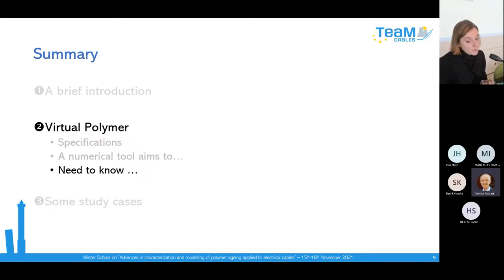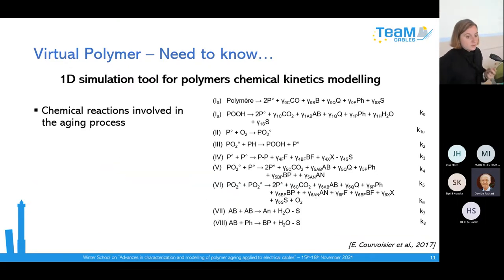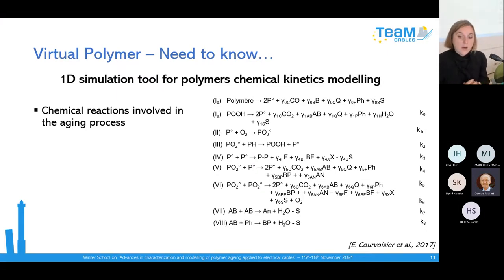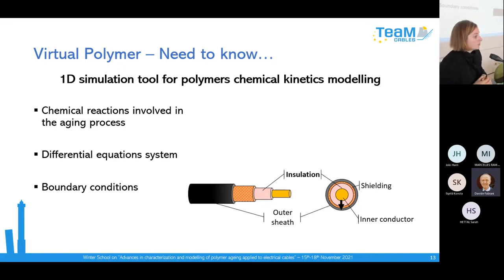For that, you need some input data. For virtual polymers, you need to know the chemistry of the polymer and the microstructure. You need the chemical reactions involved in the aging process — here it's an example from the PhD thesis of Emilie Corvoisier, with chemical reactions also explained by Xavier. You also need to know the differential equation system and the boundary conditions, such as the diffusion coefficient and sometimes evaporation.